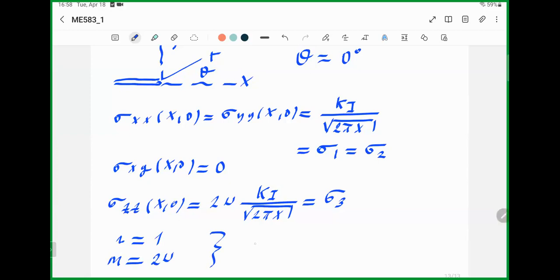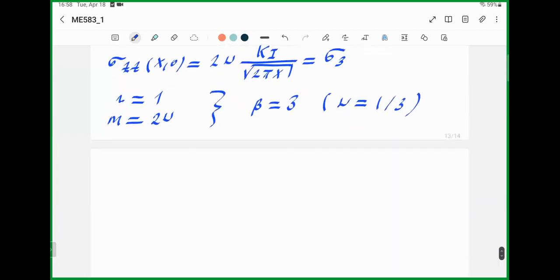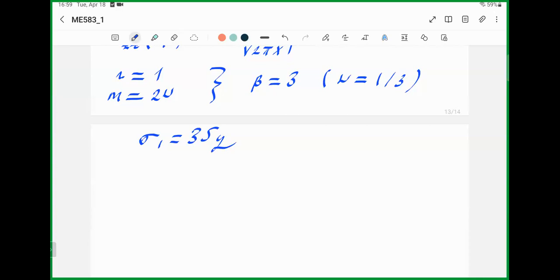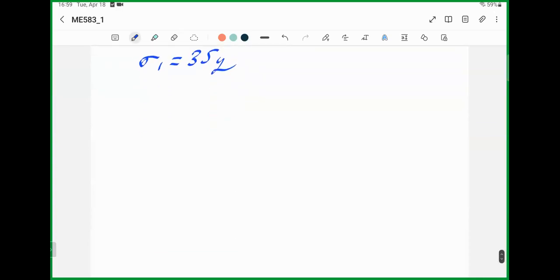The plastic constraint factor depends on ν. Approximating ν as one-third, the effective yield stress is larger — sigma_1 equals 3Sy at the point of yield. This larger stress is required to plastically deform the material, and this leads to a smaller plastic zone at the crack tip. An approximate stress distribution can then be generated for thicker specimens.